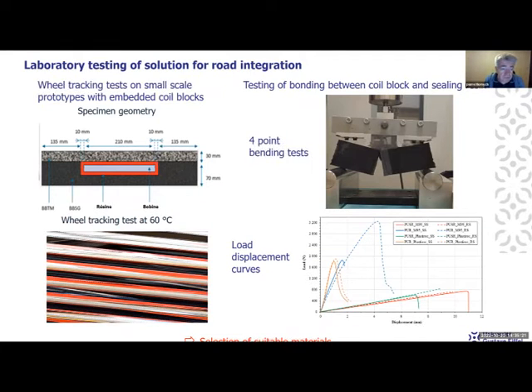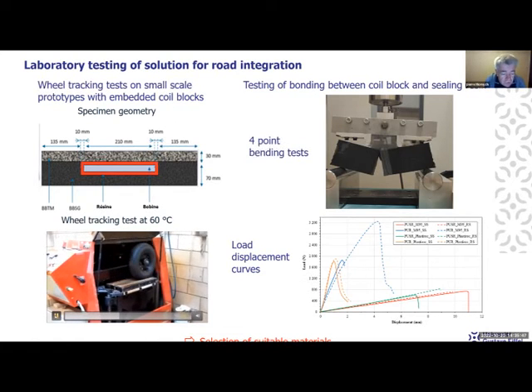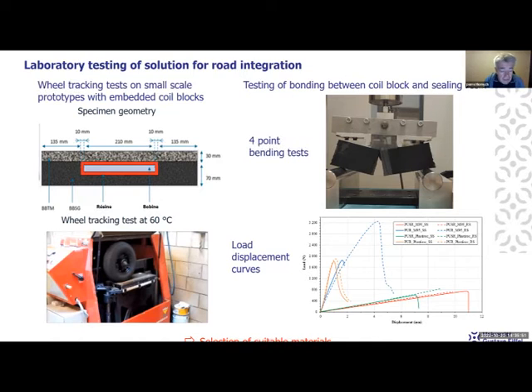And then we also wanted to test the mechanical behavior of the system in asphalt layers. For that, we proposed two tests. First, we did wheel tracking tests, which reproduce the loading by a wheel on a small scale specimen. So we built small scale specimens with two asphalt layers in which we embedded these coils. The wheel tracking test is normally used to test the rutting of asphalt materials and consists in applying a rolling wheel load on a plate. We used this test on these specimens, and we tested different materials for the coil block and also for the resin used to seal the block in the pavement. So we were able to select appropriate materials for the block and for the resin.